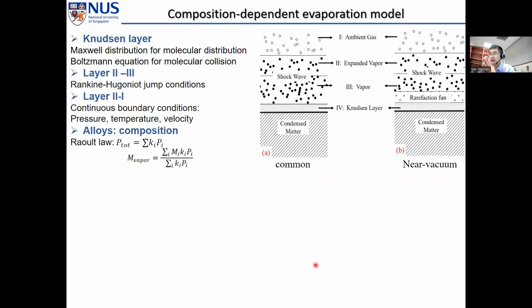And for laser powder bed fusion, mostly it's keyhole mode. And for keyhole mode, the evaporation is very serious. But traditional models didn't consider the compositions. So here we develop our own composition-dependent evaporation model based on the Maxwell distribution for molecule velocity distribution, the Boltzmann equation for molecule collision, and also the boundary conditions where we consider the compositions.